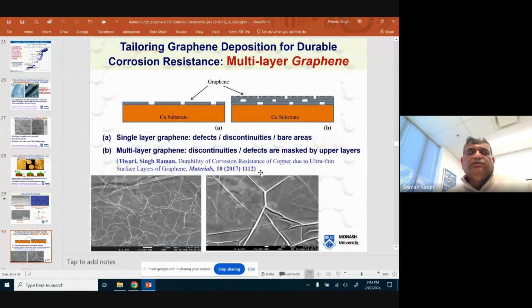So what to do? Either you find a way to form a continuous layer of graphene, and it is a painstaking job. Ajay's group would do it, and we got those samples and gave very good corrosion resistance. But in normal process, it is not easy to have discontinuity-free graphene. And if you have discontinuity, corrosion will be happening at those locations where you have bare area.